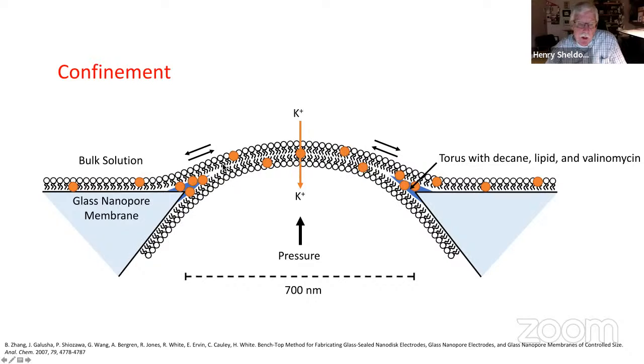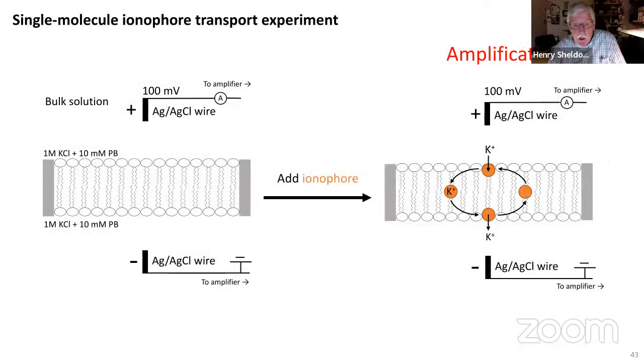And so instead of having 10,000 or 1 million valinomycins in the bilayer, which is typical of these classical measurements, we just have a few, and that puts you in the ballpark for making single molecule type measurements. And so the experiment is simply to use two silver chloride electrodes and apply a potential, and then measure the current that flows across the bilayer.